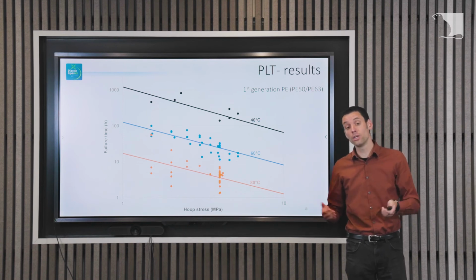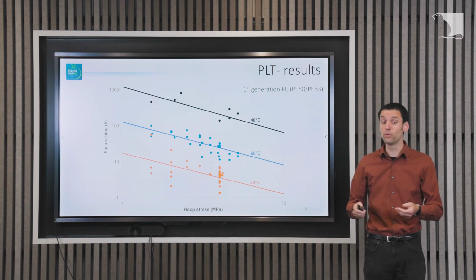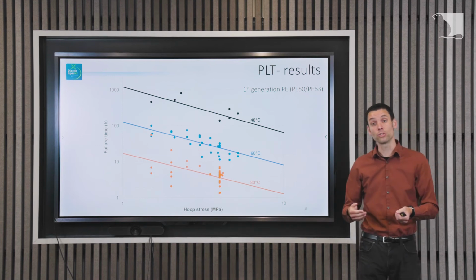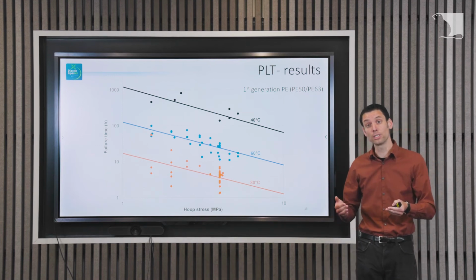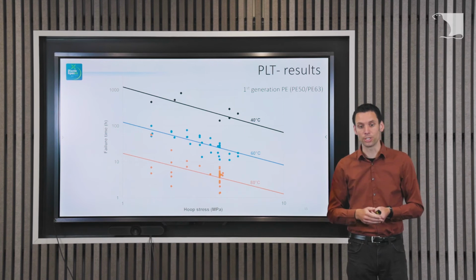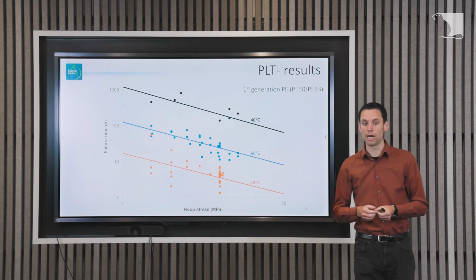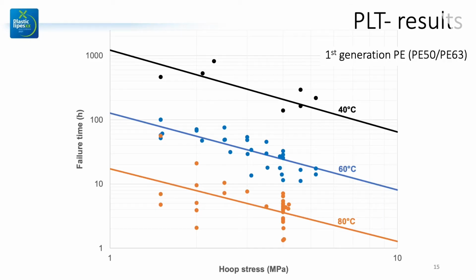So actually one of the advices also to the end users or the pipe owners was, if you have problems with point loads, reduce the internal pressure. That really helps. But we also sort of extrapolated it. Because we did it at 80 degrees, at 60 degrees, at 40 degrees, you can extrapolate it to soil temperature, and we can take into account the acceleration factor of the temperature.